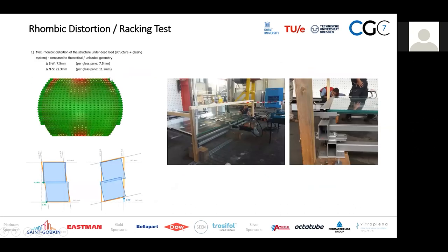What was an interesting aspect was that it's a super lightweight, weak structure. We had asymmetric forces due to wind and seismic, so we had to deal with these rhombic distortion effects. We found out in our structural analysis that we had a displacement of up to 22.3 millimeters while having a frame bite of only around 12.5 millimeters. So we built a racking mock-up and had to check that the actual frame bite, the glazing system, works without damaging the glass in a worst case scenario.